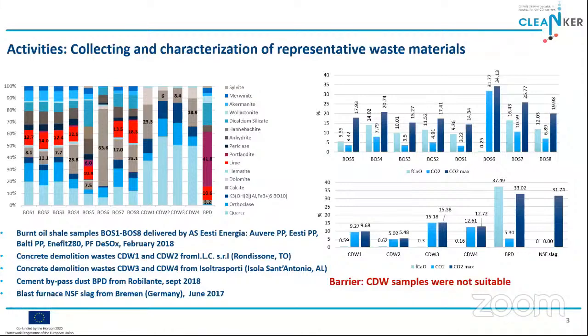These include burnt oil shale samples, concrete demolition wastes, cement bypass dust, as well as blast furnace slag from the steel industry. Burnt oil shale samples were quite promising, but unfortunately the concrete demolition waste samples were not, which I will go into detail about later. Here you can see the free lime content, which is the main contributor for the mineralization, is non-existent in concrete demolition waste, unlike in the burnt oil shale samples.